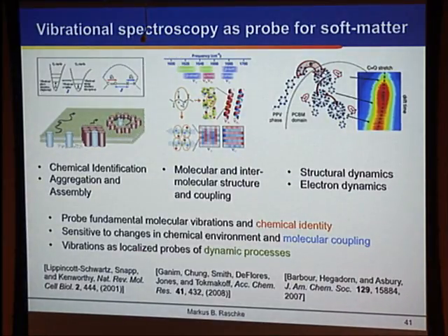we can actually use infrared vibrational spectroscopy or Raman to probe molecular matter in dense interactions. And so the way we do this is that we probe the vibrational transitions, which are characteristic for a particular chemical bond. But we don't just do it for the chemical identity as you do in vibrational spectroscopy; we also look at shifts of this vibrational transition as a result of intermolecular interaction. This is a result of the Stark effect. And so this intermolecular interaction gives rise to vibrational solvatochromism. And so this is a measure for us for the molecular coupling on molecular length scales. And then again, we'll look at dynamic processes.